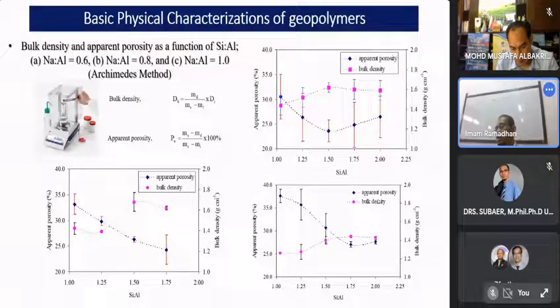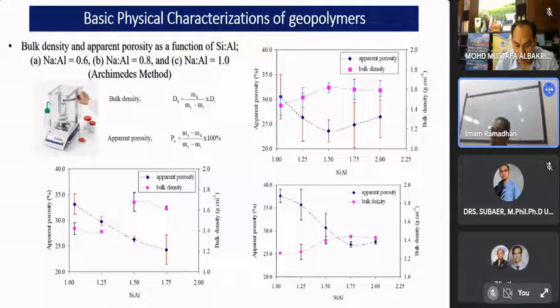And this is related directly to the strength of the materials. The fewer pores your materials have, of course, the denser they will be, and the higher the strength. So the porosity will influence your materials quite badly if you need to produce a high quality geopolymer, a strong material, so you need to control many variables or parameters in order to not introduce more pores in your geopolymer.